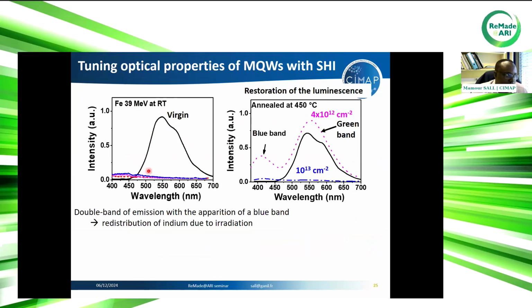We irradiated the sample at room temperature, and after irradiation, we annealed the sample at a temperature of 450 degrees. What we can see here is that we can restore the luminescence in the green band, but at the same time we create a new band here, which is a blue band in fact.